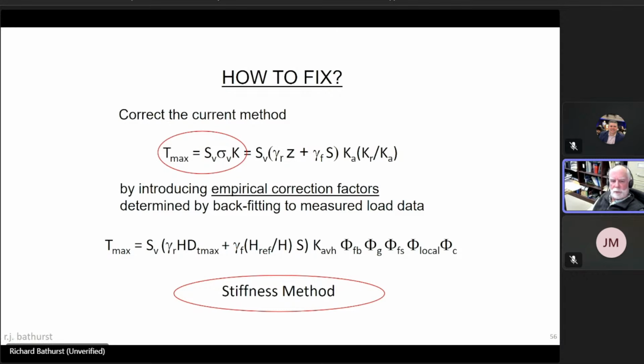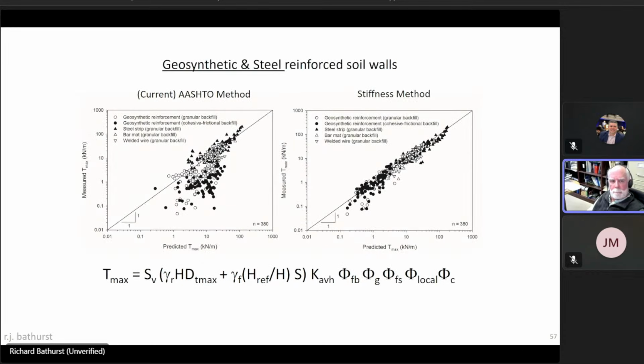And we called this the stiffness method because a major ingredient in the calculation of the maximum load was the stiffness of the reinforcement. So then when we went back to our database of both geosynthetic and steel reinforced walls, which you can see on the left-hand side, and we corrected our predictions using this stiffness method, you can see on the right-hand side, at least visually, the predictions are much better.